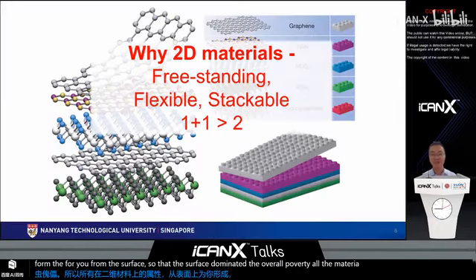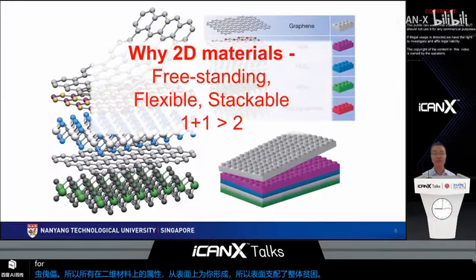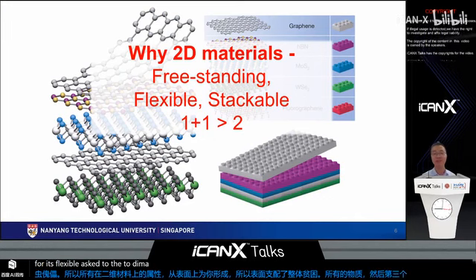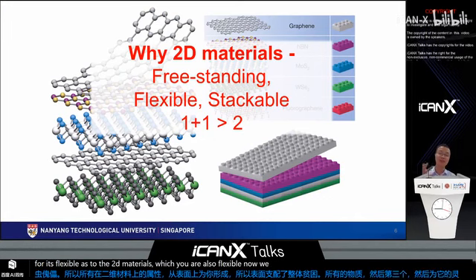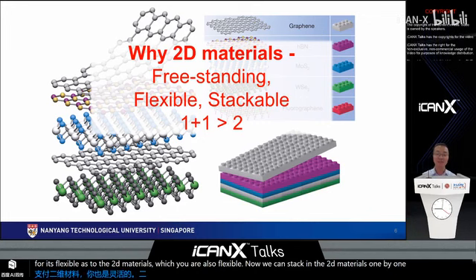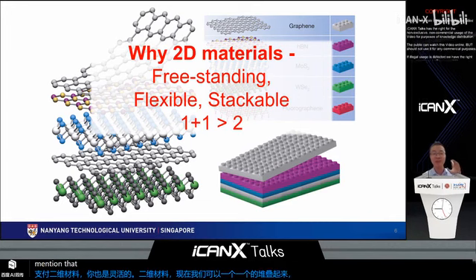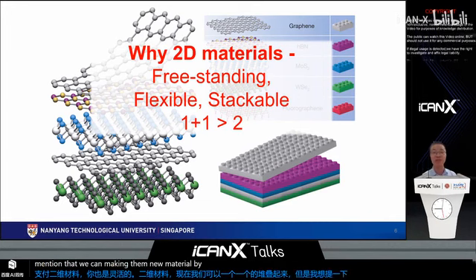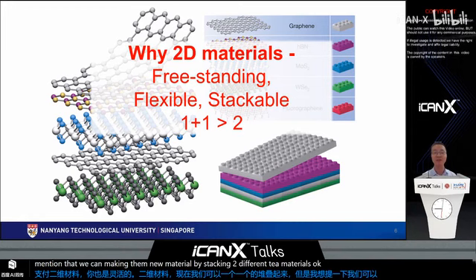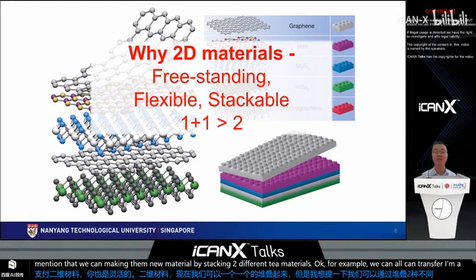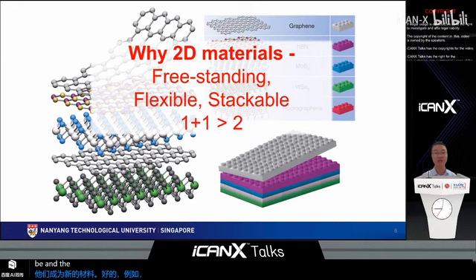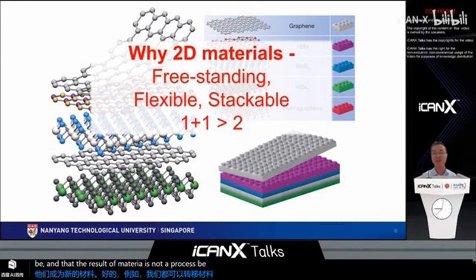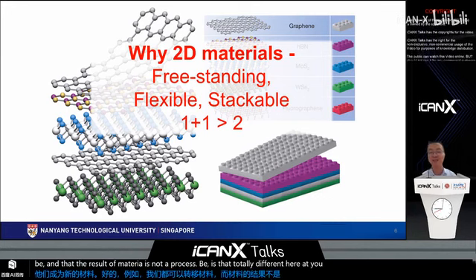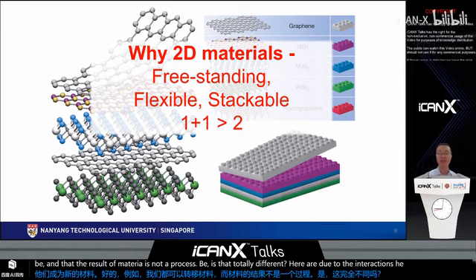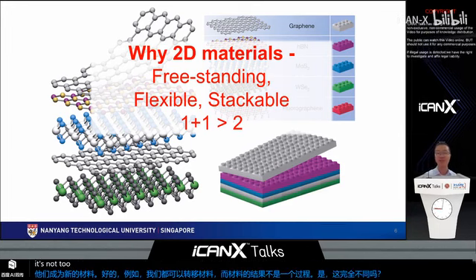And then the third one, the paper is flexible. So as to the 2D materials, which is also flexible, we can stack the 2D materials one by one. But I would like to mention that we can make a new material by stacking two different 2D materials. For example, we can transfer a material A to material B, and the resulting material is not A plus B. It's a totally different material due to the interlayer interactions. So here I call this 1 plus 1. It's not 2, it's more than 2, it's different 2.